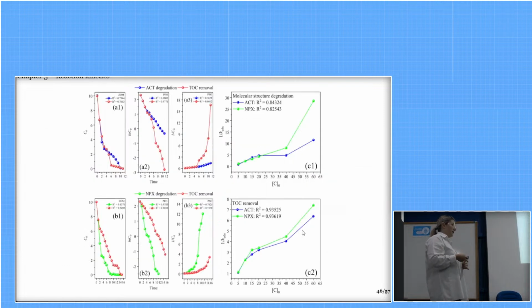Then, as we conducted the experiments, we observed through liquid chromatography and through TOC analysis that the reaction speeds were different. So we investigated the fitting of these reactions to kinetic models. All of them were better represented by the pseudo first order, which indicates the participation of reactive oxygen species. But here we observed an interesting phenomenon in the differences in kinetic rates for molecular structure degradation, by which I mean the degradation of the pristine structure, and for TOC removal, which is the conversion of the fragments to carbon dioxide and water.